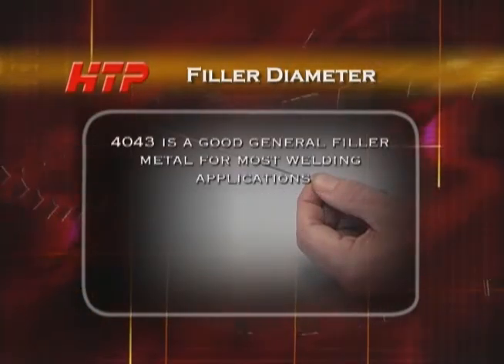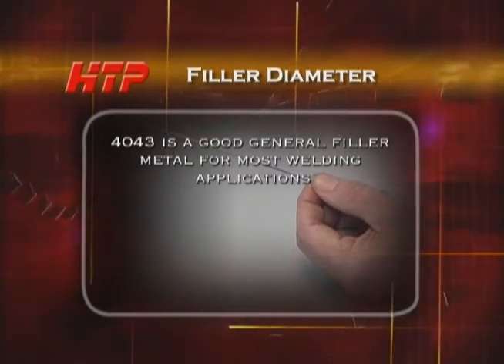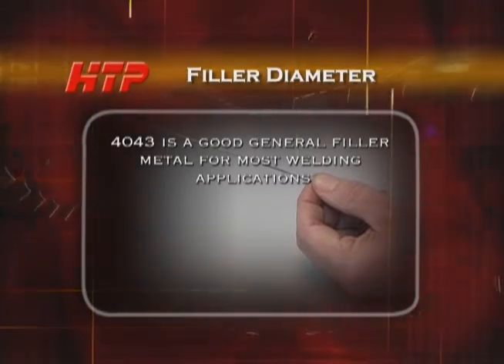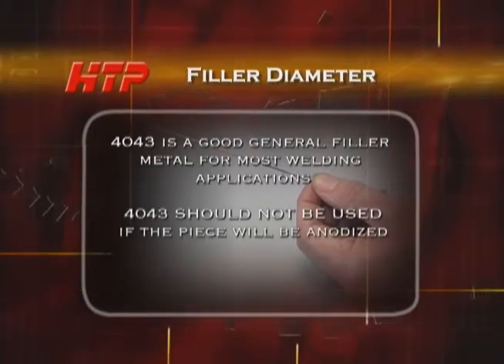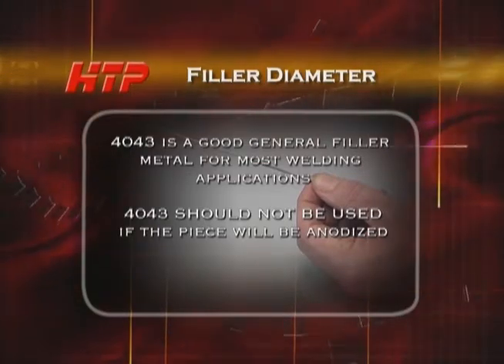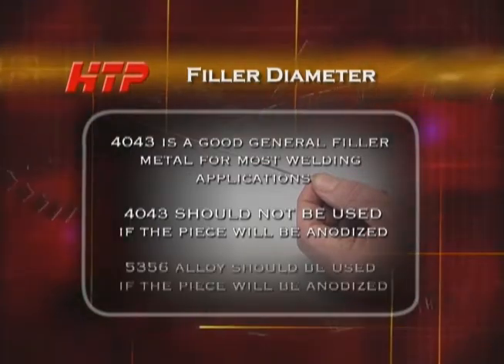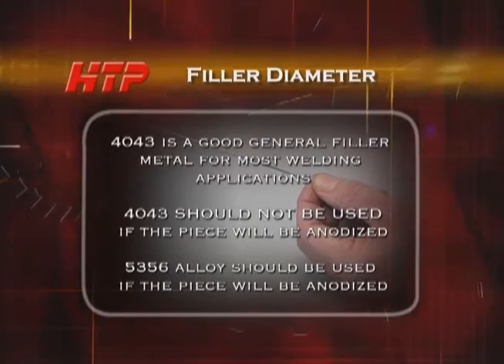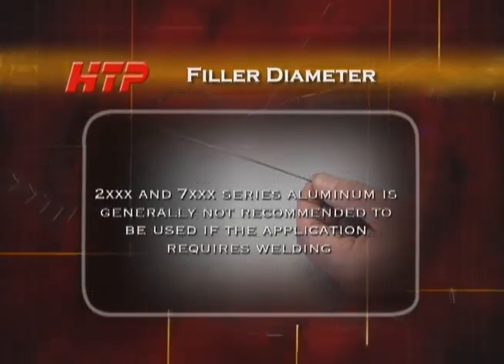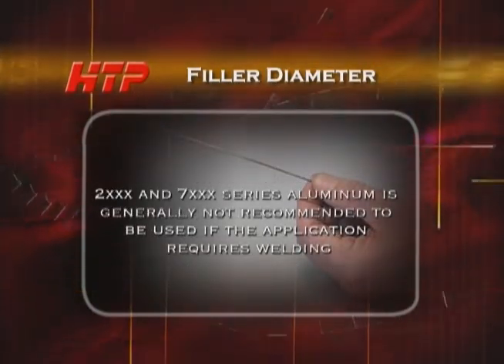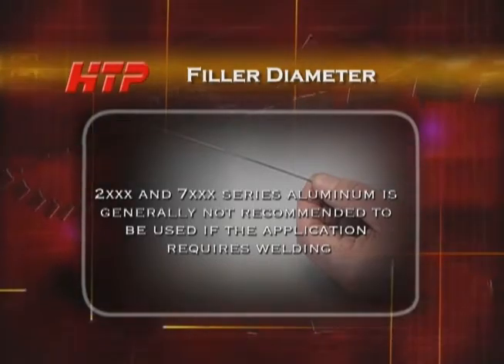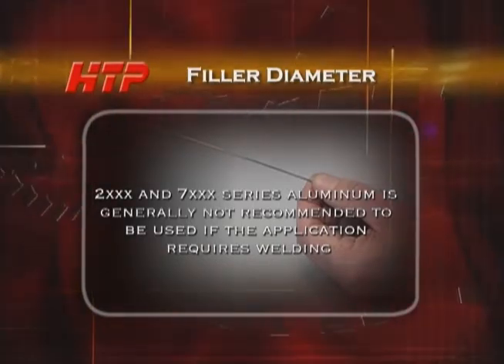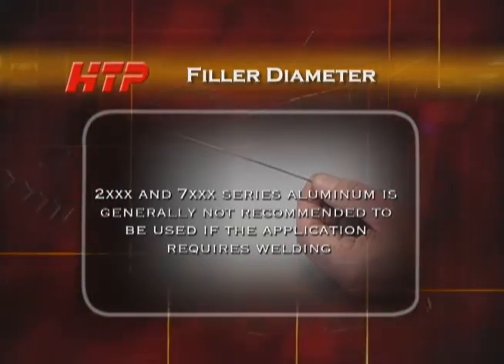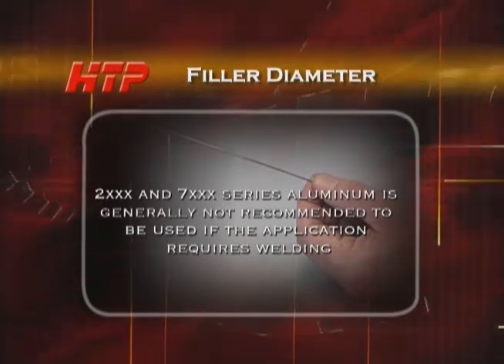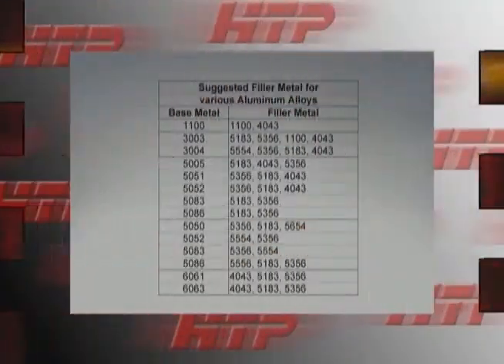4043 is a good general filler metal for most welding applications. However, 4043 should not be used if the piece will be anodized, and a 5356 alloy should be used instead. Remember, 2000 series and 7000 series aluminum is generally not recommended to be used if the application requires welding, so try to stay away from those alloys. Use the following chart as a guide.